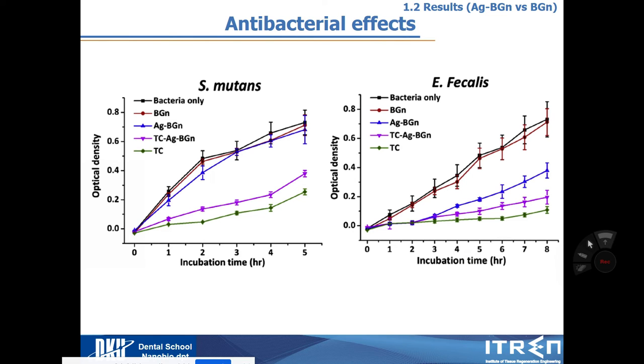So as you know, S. mutans is a major bacteria for inducing dental caries, and E. faecalis is a major bacteria in the infected pulp. So I chose these two key bacterial strains and then checked their bacterial viability in the five groups. So bacteria only shows high viability over time, and with BGN, there is nothing to inhibit the bacterial viability. So black and red are similar. AGBGN, in the case of S. mutans, has a little bit less viability, but in the end similar.